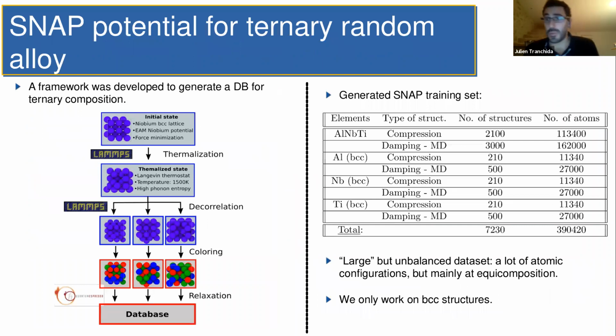Okay, so the first step of the work was to prepare a snap potential, train a snap potential for that ternary random alloy. To do that, we developed a small framework, it's more like a script basically, that's going to be running classical molecular dynamics with a classical potential with a lot of steps, at high temperature, to try to generate a lot of decorrelations between the configurations, spatial decorrelation, I would say, and then apply random colorings and then apply a relaxation to those configurations and put them in a training set.